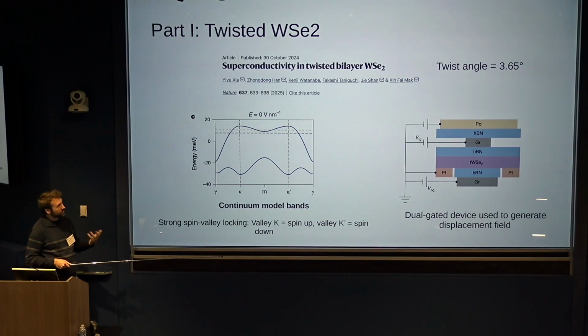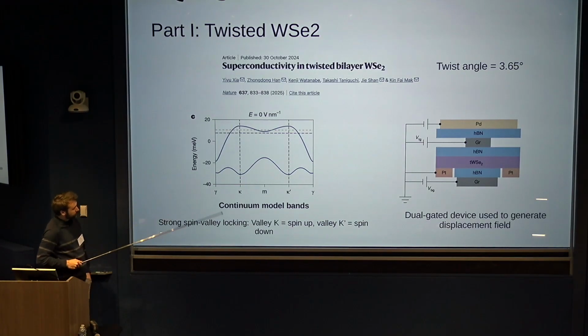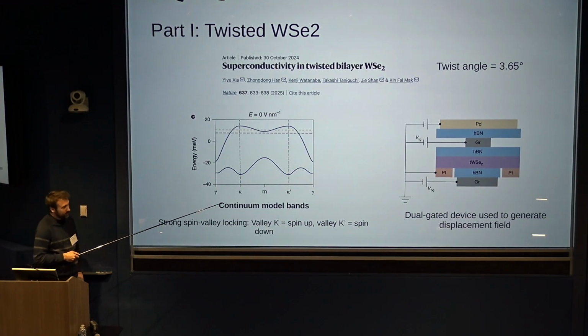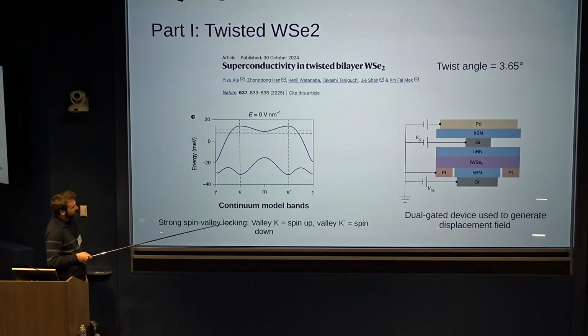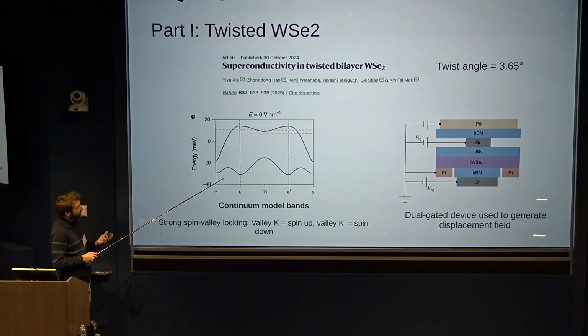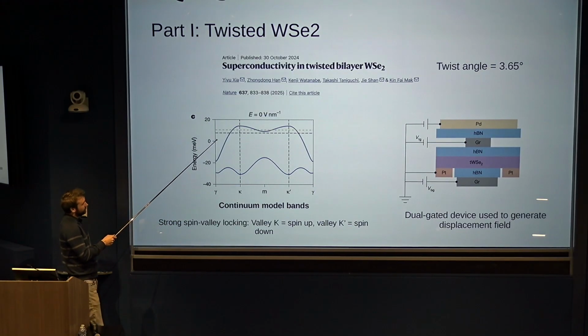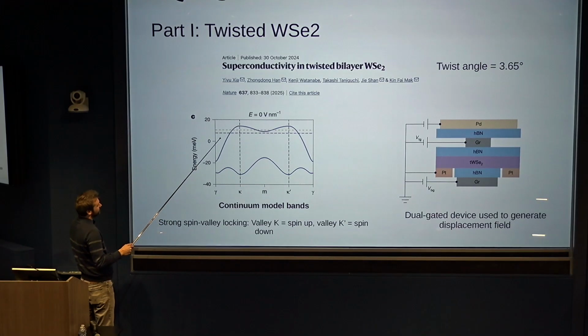And this is believed to drive the system into a more strong coupling regime. On the bottom of the slide, I'm showing the top two bands that you get from a continuum model that's supposed to describe this Moiré system. These are the top two bands in one of the two valleys. What's also important to keep in mind is that in this material there's very strong Ising spin-orbit coupling, which means that the bands in the K valley are spin polarized in the positive Z direction, and the bands in the K prime valley are spin polarized along the negative Z direction. So electrons in valley K are spin up, electrons in valley K prime are spin down. I will mostly be interested in a hole doping of one hole per Moiré unit cell, and that puts your Fermi energy right in the middle of this top band here.